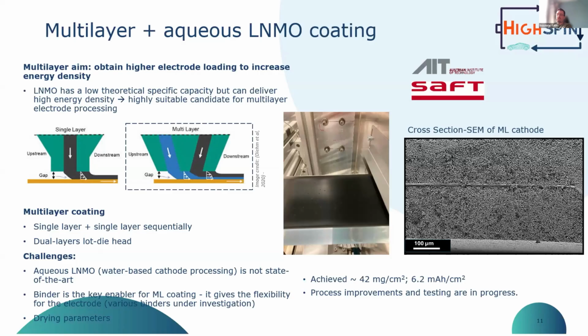So that's one aspect of the 3D electrode engineering, and the other one, as mentioned, is the multi-layer coating. Multi-layer coating means the application of one coating on top of another coating to increase the areal loading. We can do this in two ways, depending on the equipment that's available. On one hand, we can coat a single layer and then coat another layer on top of that. If you look at the left picture, for instance, you just repeat the process. Or we can do a simultaneous dual layer coating using a slot die head. And of course, there have been simulations and process parameters investigated to find the optimal settings for this kind of coating.